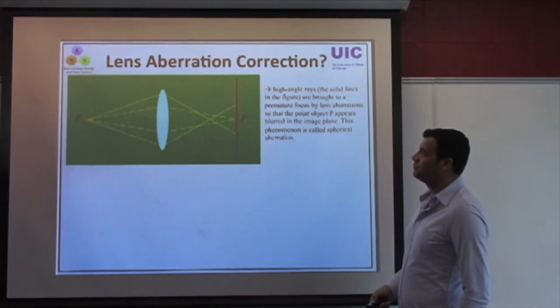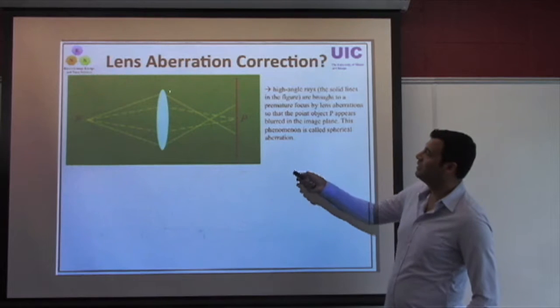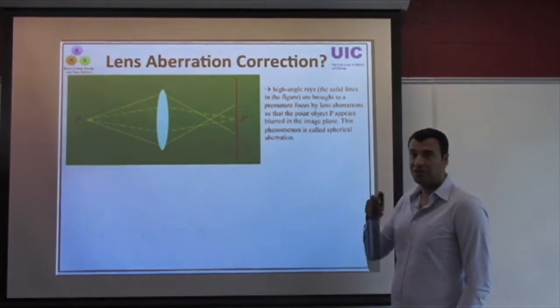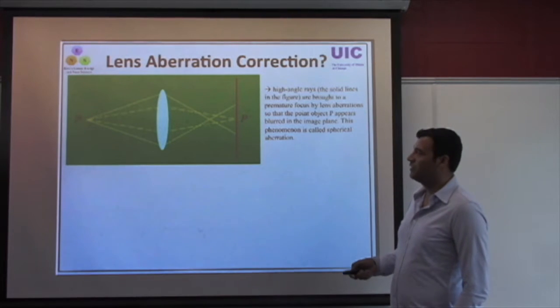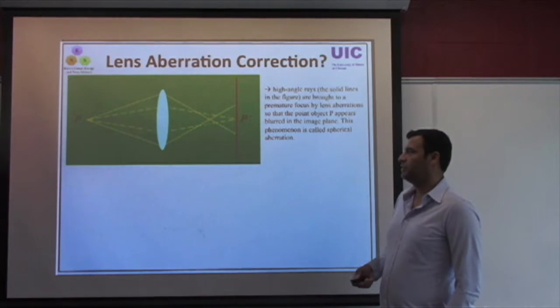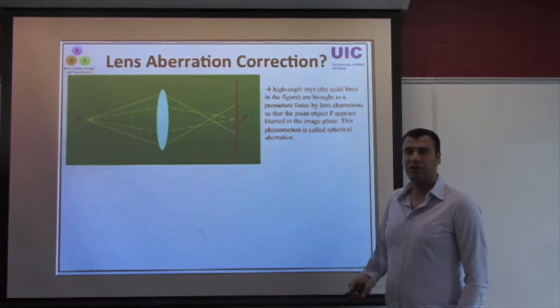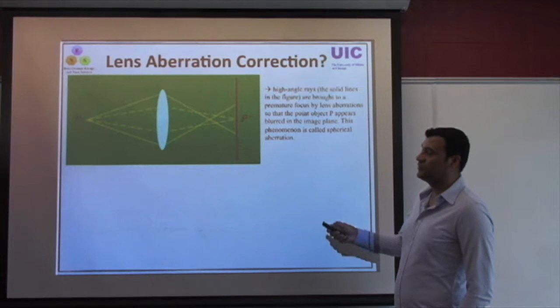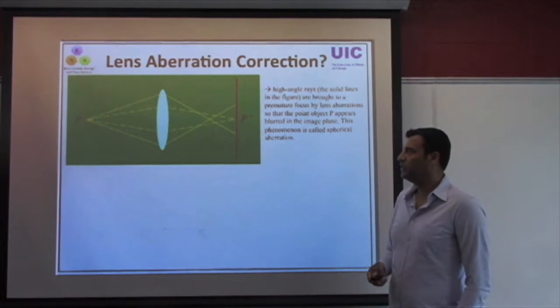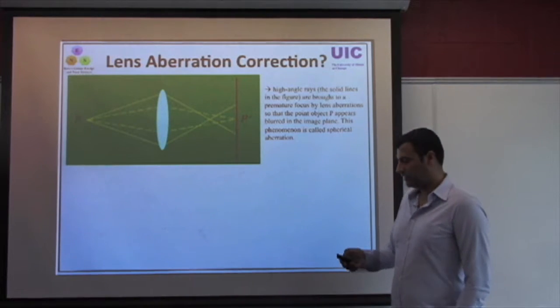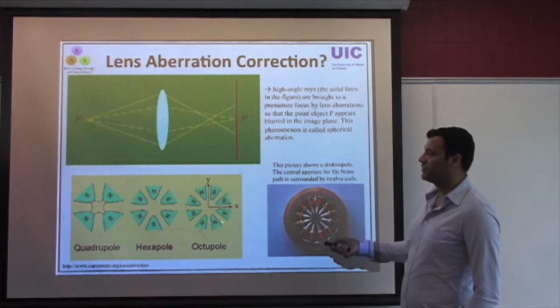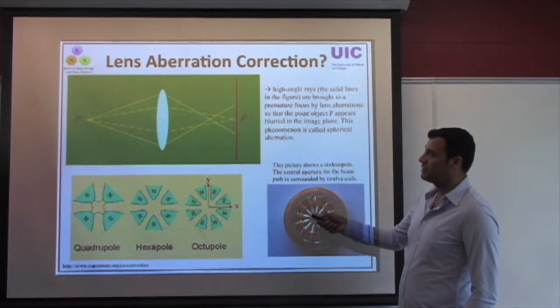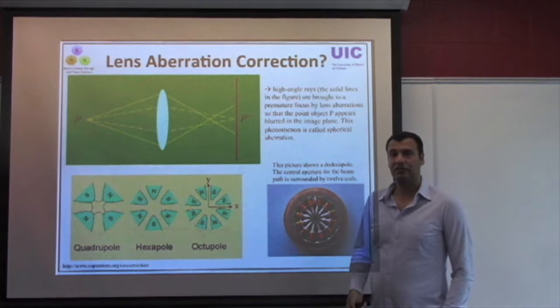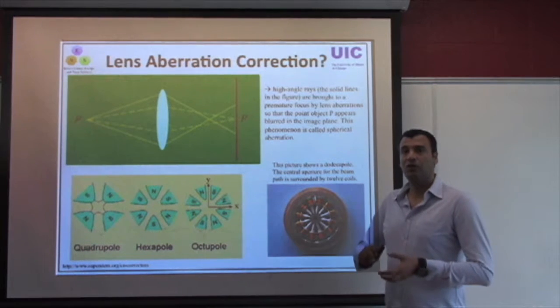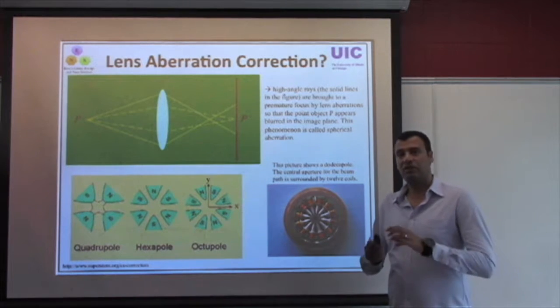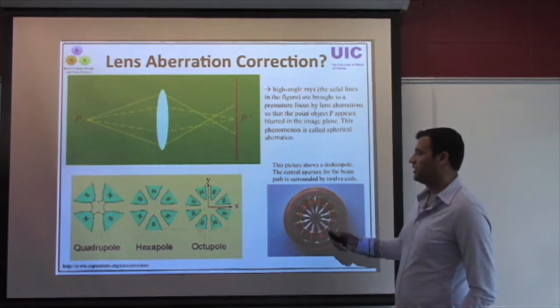So the resolution of electron microscopy was limited for many years because of these aberration issues. It was around the decade of 1990 to 2000 that there was a lot of development to correct this aberration issue, and that's why aberration-corrected electron microscopes were born. In this sort of system, the rays that have been deflected by the lenses are passed through quadrupoles or hexapoles, and they are corrected in terms of their location and behavior.